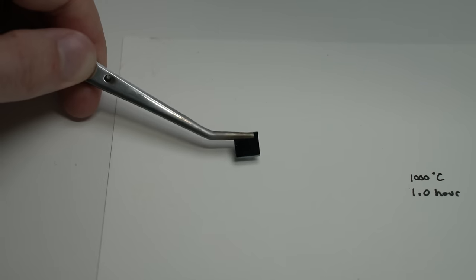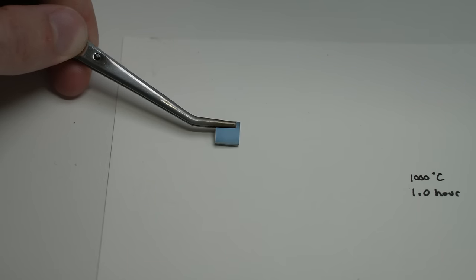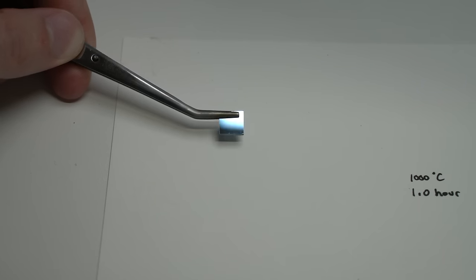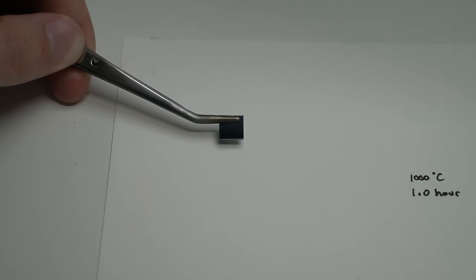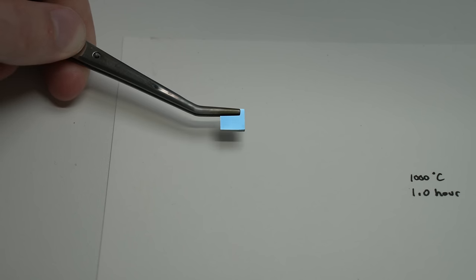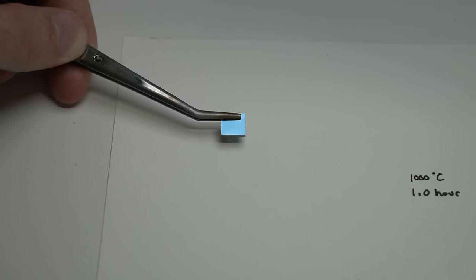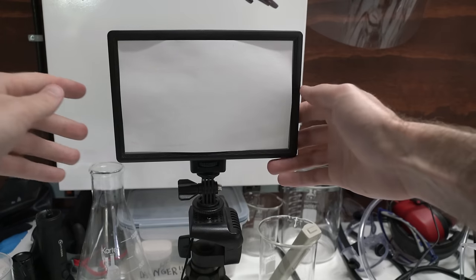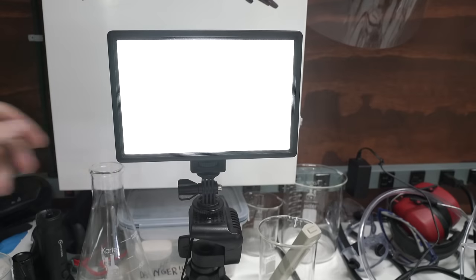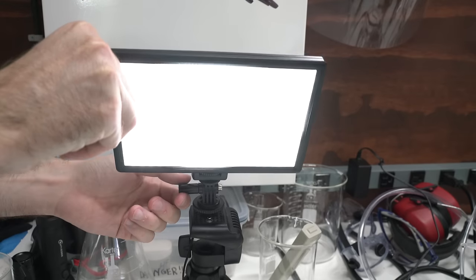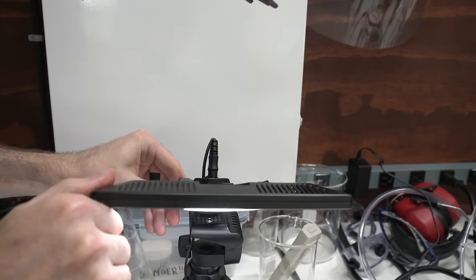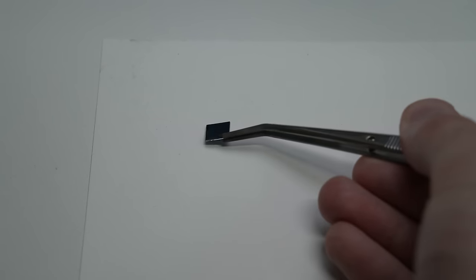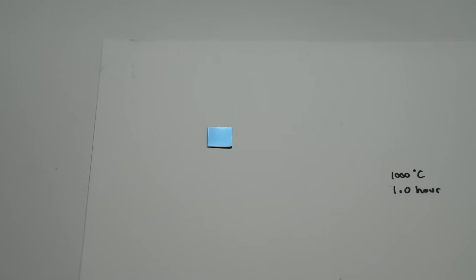Now, it can be a little difficult to view the color of an oxide layer. You'll need a good light source, something with a continuous spectrum, or high CRI. Fluorescent lights and low-quality LEDs generally don't work well. You can use incandescents if you have them, or even just sunlight. I'm using an LED panel with a high CRI, specifically made for photography. I have mine on a tripod so I can adjust the angle to my liking. I set mine up so that the oxide is viewable when the chip is lying flat on the desk.